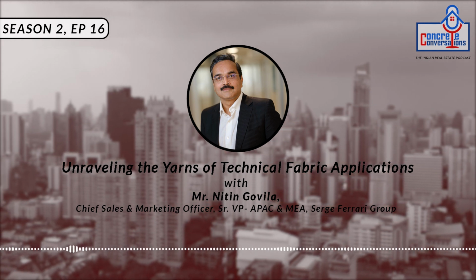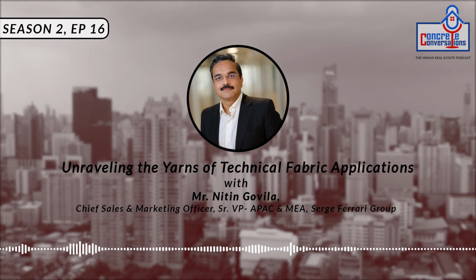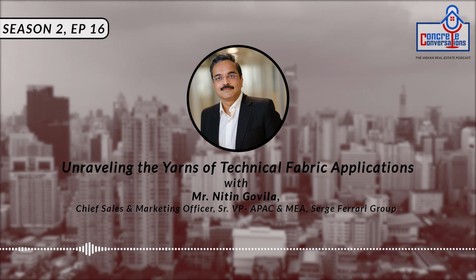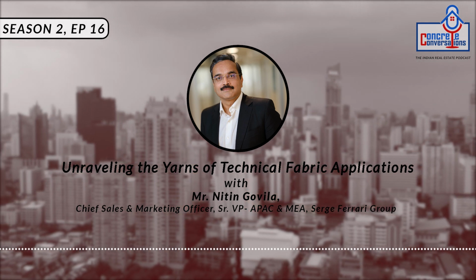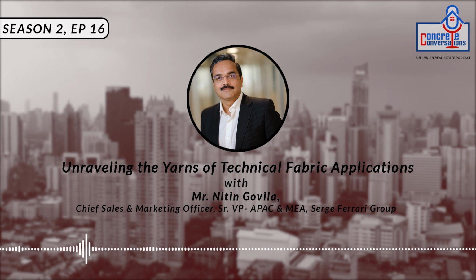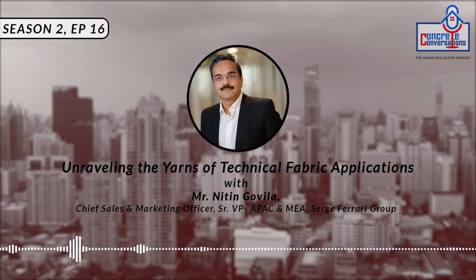Now, then the technical aspect comes. So the fabrics, or the technical fabrics, or the membranes which Serge Ferrari sells, are generally of two kinds, or three, I would say. The primary one is polyester yarns, which are coated with PVC. And the technical element comes with the mix of the yarns, what kind of yarns we are using, how they are woven, how they are coated, what kind of coating we use, both sides, one side, the thickness. So all those elements form the technical features or the data sheet of that particular fabric, which then, depending on the application or the requirement, you choose accordingly.